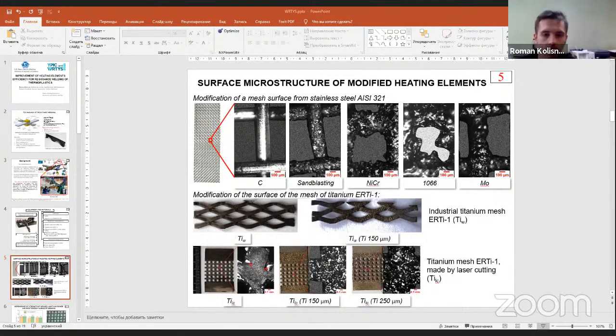The specific area in this case is higher, and mechanical contact between polymer and the heating element is better. You need to know that with increasing the depth of the coating, the specific area additionally increases. By using this modified heating element to weld the butt joint with chromium and titanium coating, you can see from the diagram that the increase in strength is up to 10% on a model high density polyethylene.